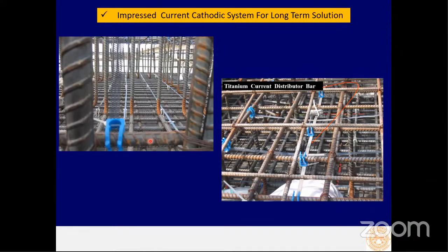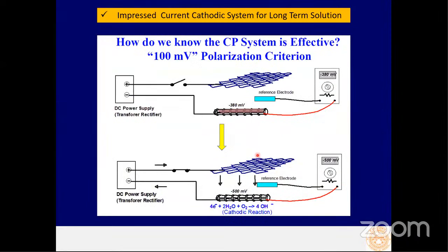material and also the protective system like the impressed current cathodic system. This is designed for the long-term solution. For example, on the existing rebar of the pier cap, we install a titanium current distributing bar that is going to serve as one component of the circuit. So this titanium mesh is going to work as an electrode. And after we connect the rectifiers, which is the DC power supply, between the reinforcement and that titanium mesh, it's going to form a cathodic reaction. So based on that, we help the existing rebar no longer be subject to the corrosion problem.